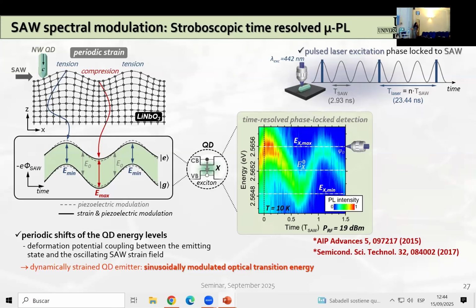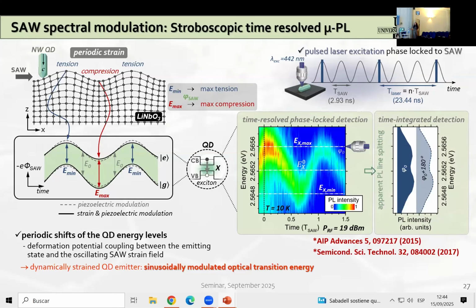This is also very well observed in stroboscopic time-resolved micro-PL experiments performed under pulsed optical excitation synchronized with the acoustic wave, where you can actually see such sinusoidal oscillation of the transition energy during the decay. Now, if we integrate this over time, we obtain such apparent splitting of the PL lines. And in this context, these minimum and maximum transition energies correspond to the acoustic phases at which the tensile and compressive strain have the maximum value.